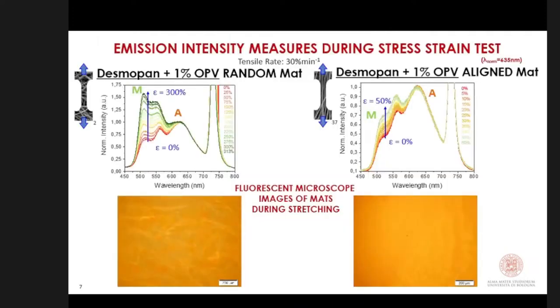Here there is a short video of the electrospinning process where you can see that the starting solution has a green emission because of the dispersion and not aggregation of the dye. But with the formation of the fibers and the evaporation of the solvent, you can see how the fibers in the collector look orange. So how is the mechanochromic response of these materials?